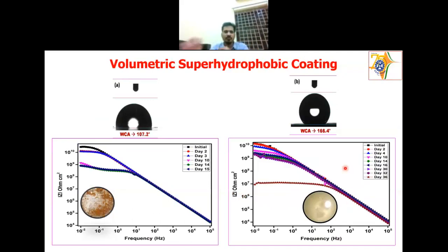And we have done some impedance analysis also for both the coatings. You can see initially both the coatings have very high impedance value. Generally, if the impedance value is higher than 10 raised to 6, we say it's very good corrosion protection, but superior and excellent can be classified when the value is higher than 10 raised to 10.